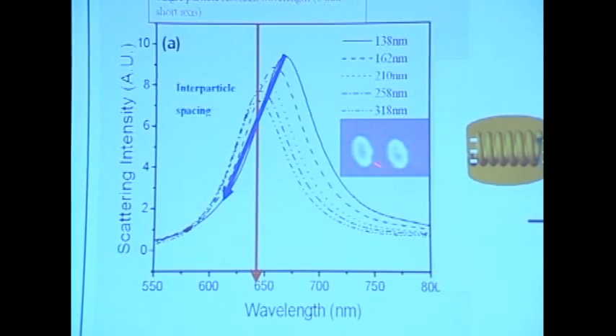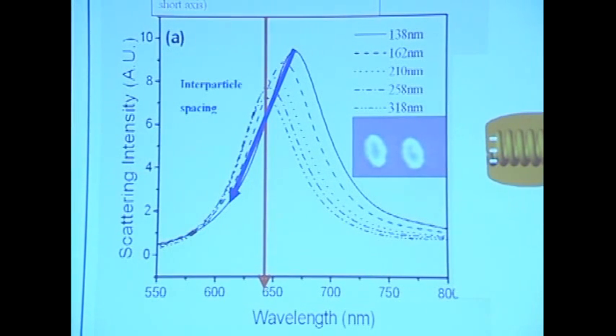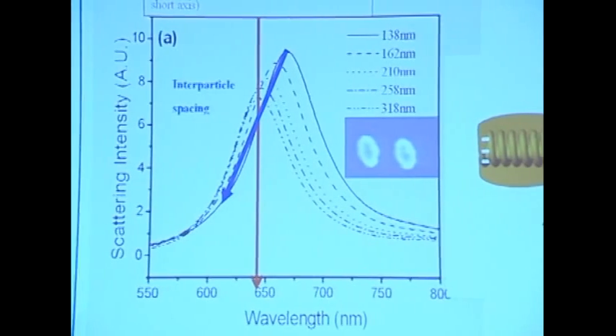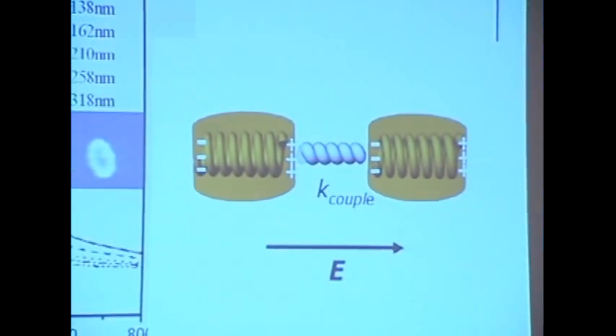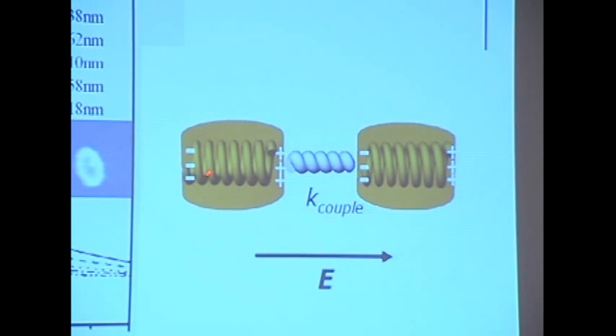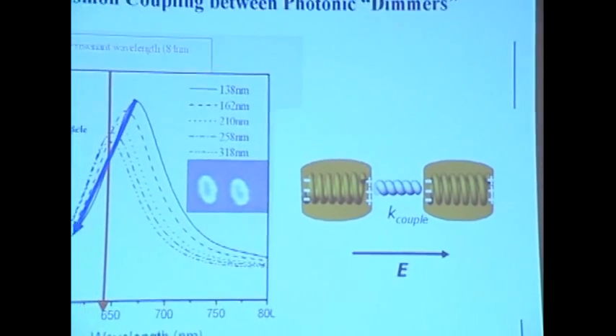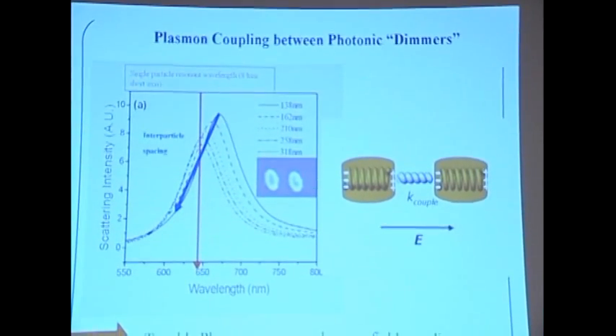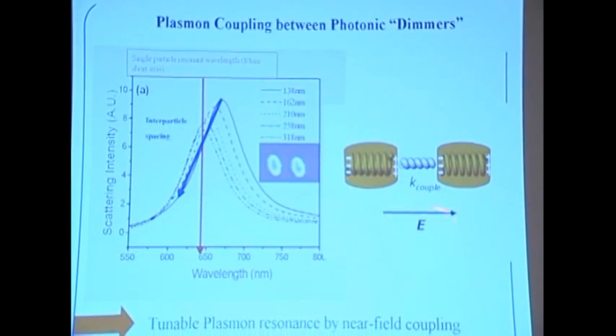It's pretty simple, actually. You can observe a redshift as you bring the two particles closer and closer. Why is that? I use this mechanical spring resonator to show it. It's pretty easy to understand. You have two plasmonic resonators, which are essentially charge oscillations on the particles. When you have an electric field this way and they get fairly close in the near field, the positive and negative charges start to talk to each other. That reduces the spring constant, essentially, so the resonance of this system is reduced, omega equals the square root of k over m. If the spring constant k is reduced, omega is reduced, so that's the redshift. That explains it with a simple model.